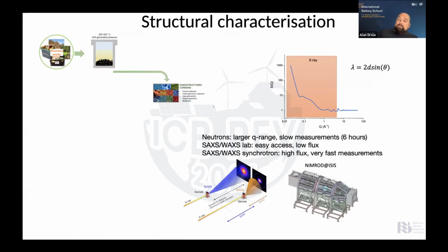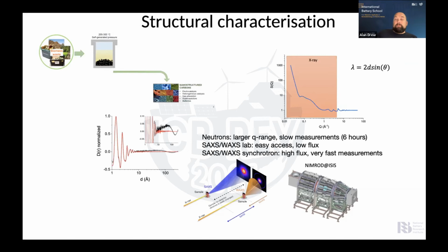Okay, then we put it into an X-ray scattering machine, a small angle X-ray scattering machine, which gives you some peaks. These peaks correspond to structures in the material. So here we can tell pore size distribution. Here we can tell crystal structure.